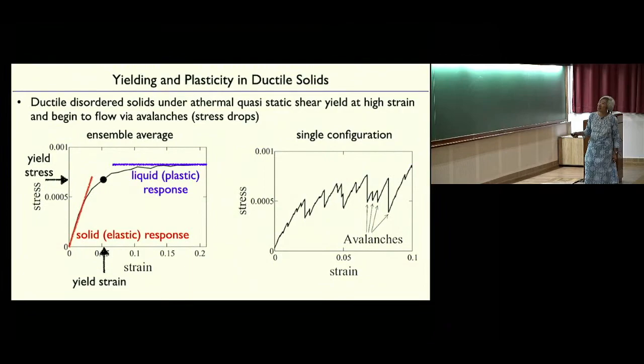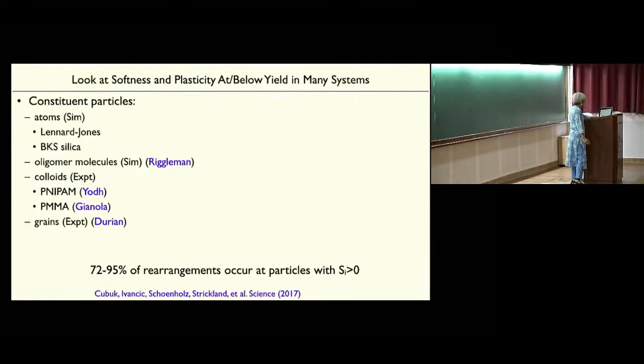Okay, so the stress, as you see, if you look at an individual configuration, this is the average behavior. If you look at the individual case, it's much more interesting, right? What you see are these little stress drops, where you have not just a single rearrangement, but one rearrangement can trigger another and another. You get these avalanches of rearrangement. You get what's called crackling noise.